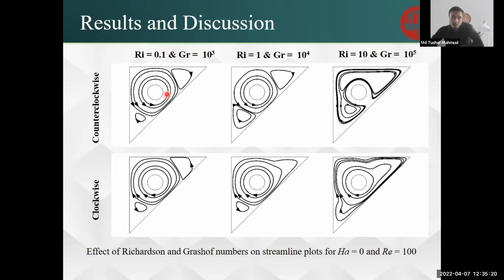So if we move on to results and discussion, we have used the rotation of the cylinder, and we have the results for both clockwise and counterclockwise rotations. We have already seen that the Richardson number represents whether the convection is natural or forced convection. For lower Richardson number, the convection is mainly dominated by forced convection, which is visible here. The rotating cylinder is guiding the flow here for Richardson number equal to 0.1. And if we increase the Richardson number, the flow is dominated by natural convection.